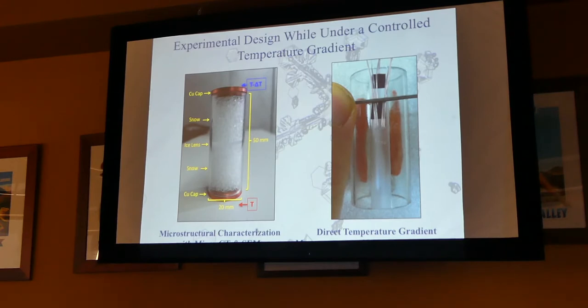And then also, in a different setup, we put little micro thermocouples that are 79 microns at the bead, above and below that ice lens, so we could see: is there a temperature gradient above and below there that we're not measuring with our big thermometers, but maybe we can measure with these little tiny thermometers, right? So that was the idea.